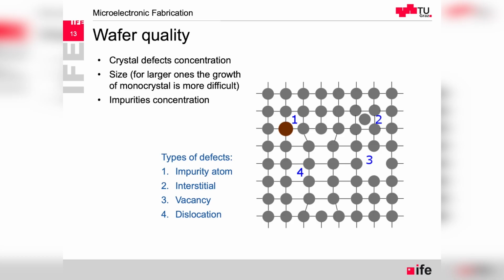One important aspect is the wafer quality. So we have some impurities in the crystals, partially the dislocations that are here, which can come from thermal problems during cooling, and therefore we have to cool as slowly as possible. But there can also be missing atoms, which is a vacancy, or an interstitial, which is an atom that is not located in the crystal structure. And also we can have an impurity atom, which will obviously be a different size than silicon atoms, causing some fluctuations in the crystal network.